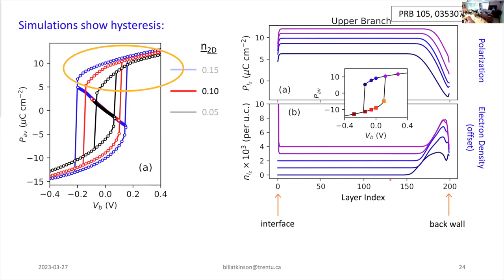So does this sharp transition in the hysteresis curve correspond to suddenly filling a new one of those narrow bands? It looks like there's a notch that just disappears going from black to the next line. What happens is, as you're compressing the charge density more and more towards that back wall, you're changing the confining potential and the profiles of these bands, so that they spatially overlap a bit. That XY band is always filled. It's the lowest energy band in the system. It's just not spatially separated from the other bands when I have a high bias voltage.